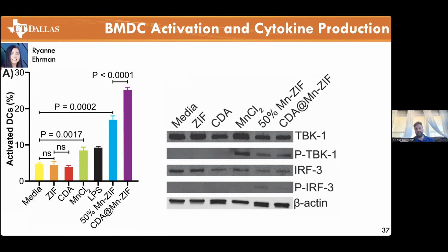cell activation. And we can show STING activation using this Western blot. Essentially, we can show phosphorylation, which are these dark patches here, of key proteins that are involved in the STING pathway. So if they're phosphorylated, then the STING pathway has been activated. And you can see that with manganese chloride, you get these same bands as well as ZIF. Now, of course, you can't inject manganese chloride into a person. It's neurotoxic, so you have to keep them all combined into a nice little nanoparticle so that it doesn't just diffuse everywhere and cause general systemic toxicity.